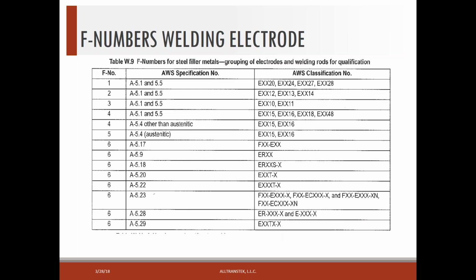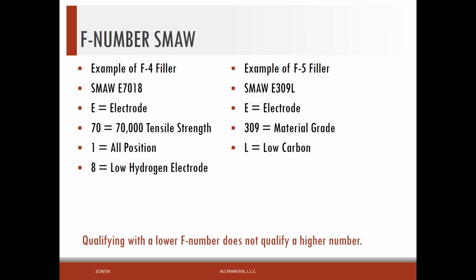Similar with F numbers, Mike talked about F numbers earlier. This is the table that breaks down what the different F numbers are. So like a 4F number would be, if you look at the section, a very common electrode we use, like 7018. This just breaks out the different F numbers, and the next slides will show you a little bit better. So like 7018, which is a shielded metal arc, so like stick welding process. The 70 is 70,000 tensile, 1 is all position, 8 is low hydrogen. That would be an F4 filler metal.